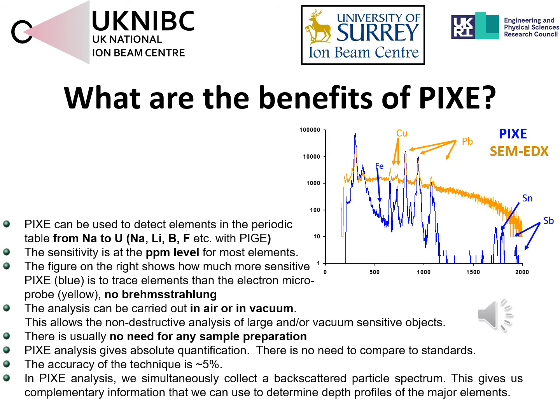And the figure to the right shows a comparison between PIXE and SEM-EDX. So it's a very analogous system, apart from with an SEM, of course, you're using an electron beam initially to produce those characteristic X-rays as opposed to a proton. And because you're using an electron beam in an SEM, you have a Bremsstrahlung background, which is shown in the yellow on the picture to the right there, and that means some of your trace elements get lost. So the sensitivity of SEM-EDX is low by comparison to the sensitivity of PIXE. Because we're using a proton, there's no Bremsstrahlung from the initiating beam itself. So we have much greater sensitivity in PIXE than there is available in SEM-EDX.